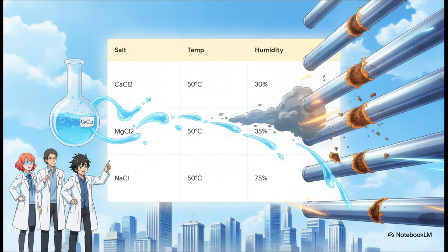But here's the thing, not all environments, or salts for that matter, are created equal. When researchers tested different salt solutions at 50 degrees Celsius, that's about 122 degrees Fahrenheit, they monitored the deliquescence point. That's just a fancy term for the relative humidity required for the salt to actually absorb moisture and become a dangerous liquid. Sodium chloride? It needed 75% humidity.